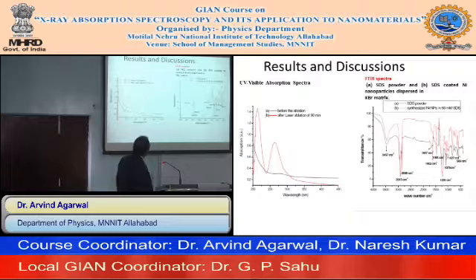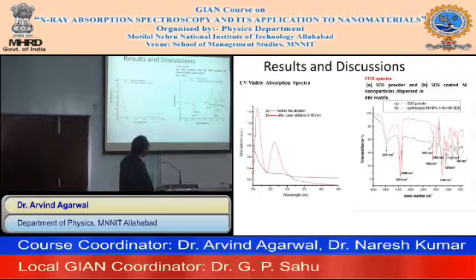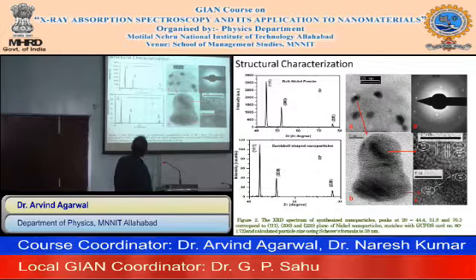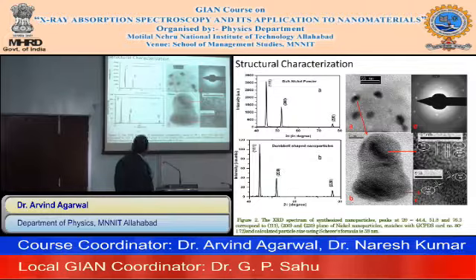These are some results from the FTIR spectra, with peaks nomenclatured according to the standard references. The XRD data shows peaks identified at (1 1 1), (2 0 0), and (2 2 0), with 2θ values at 44°, 51°, and 76°.